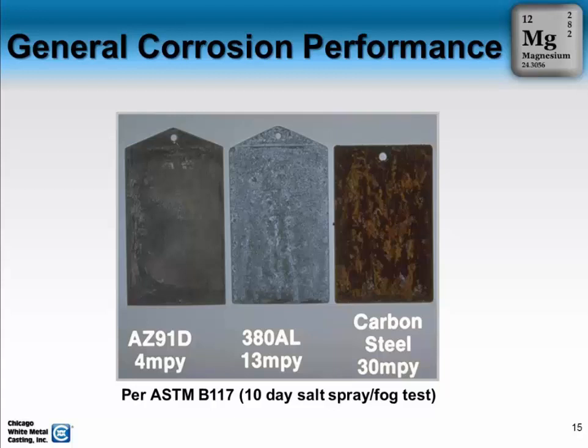Back in the early days of die casting, yes, magnesium hadn't been refined enough to where they understood what was happening, but with very low percentages of iron, nickel, and copper in the alloys that we use now, AZ91D is actually outperforming aluminum and certainly outperforming carbon steel. What you see on the chart is showing you the mils, or thousandths of an inch, that you would lose per year. MPY stands for mils per year. So magnesium 4, aluminum 13, carbon steel 30. This is according to testing that's been done under ASTM B117, a salt spray and fog test. So the high purity alloys, the D version of the alloy that we're using, is no longer an atmospheric corrosion risk.